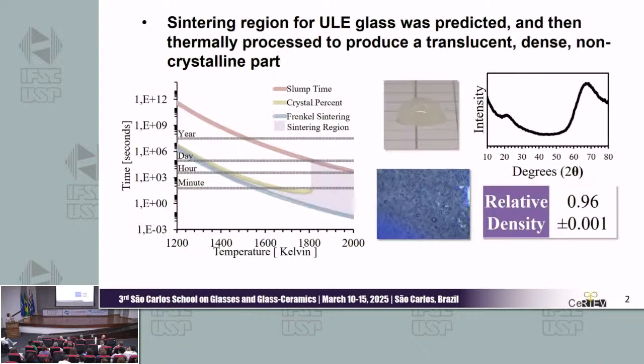So on the left here is an example of my model. If we know some physical parameters of a glass system, we can make this model for any system you can think of. The bottom line indicates when we have densified our glass. The middle green line indicates when we have crystallized our glass to observable crystallinity under XRD. And the top red line shows when our glass has deformed enough that we no longer have a part that looks like how we want. So if we print a beautiful statue, we don't want it to fall over and look gross.